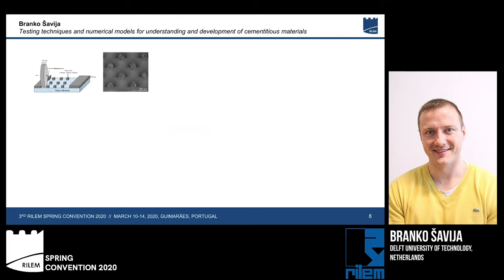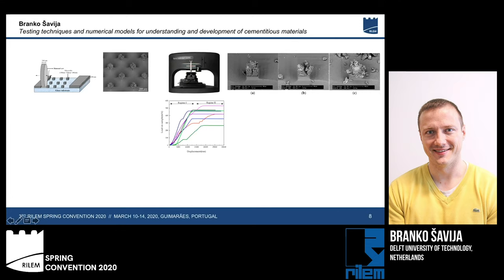Now, for this, we typically use a nanoindenter, which is also used for indentation and elastic moduli determinations of materials. We adapt the setup so we can directly test the mechanical properties of these small volumes. This is what it looks like in an SEM. Because we cannot do direct tension experiments, unfortunately, we subject these specimens to different forms of splitting. And as we increase the load, the specimen, of course, breaks in the end. During this process, we're able to measure the load displacement curves that our material can sustain.